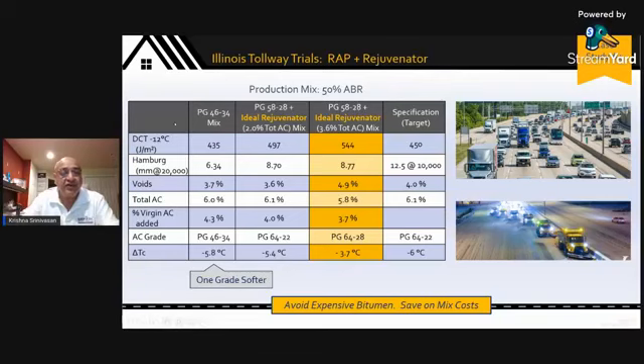Remember, I mentioned to you in your selection criteria for rejuvenators, one grade softer bitumen. The Illinois Tollway asked us to make a mix, compare one grade softer versus just regular grade bitumen with our rejuvenator. Across the board, you can see the properties are superior, are better, meet the specification. They were so happy that they asked us to put down a stretch. By the way, we put down, as part of our trial, maybe 4 or 5 days worth of production, and put down maybe at least 10, 12 kilometer equivalent of lane kilometers of highway: base course, surface course, overlay mixes, shoulder mixes, etc., etc.